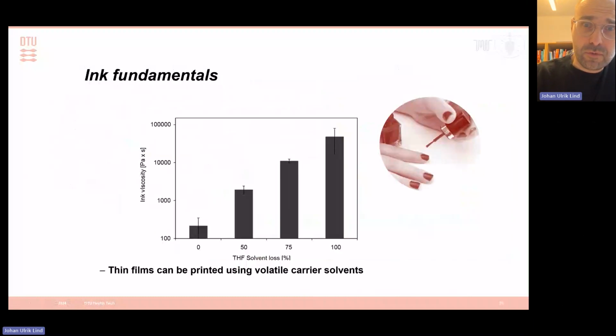Okay, so now to the second part of the talk, and I'm going to try to merge these topics as we go along. So we also have a parallel activity about soft electronics. When we think about printing soft electronics, we really like to work with dilute thermoplasts. So essentially, the inks that we're applying now are not traditional shear thinning inks, but they behave more like nail polish, where we have a volatile solvent that evaporates as soon as you extrude it, meaning that you get a very rapid increase in viscosity, and that prevents flow. So this is a technique that is really good for printing thin films.